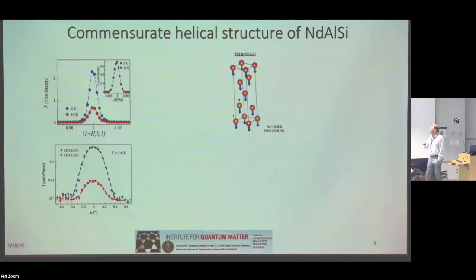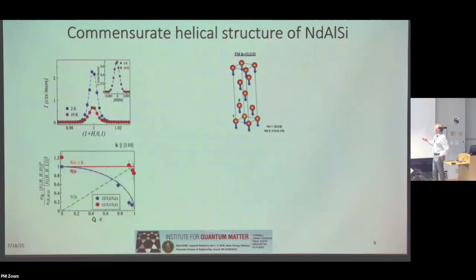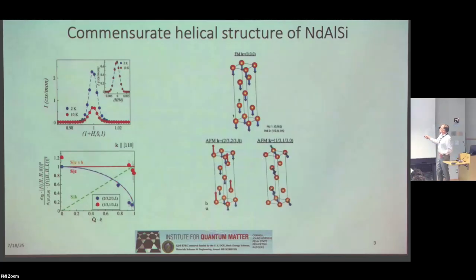And so we have two types of commensurate antiferromagnetic Bragg peaks. There's the 2/3, 2/3 and 1/3, 1/3 Bragg peaks, and they actually correspond to two different polarized components. One component is polarized along the c-axis, and the other component is polarized in the perpendicular direction. And so these are those two components. The 2/3, 2/3 looks like this, and that's the transverse component, which we also see. It's very clearly observed. All of these 1/3, 1/3 points are associated with this part of the structure. So all of these get superimposed.